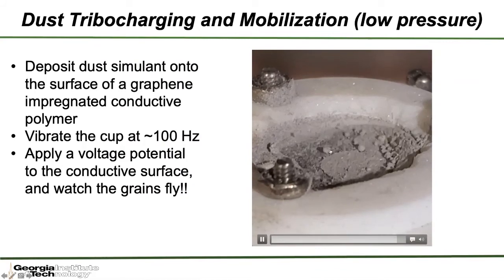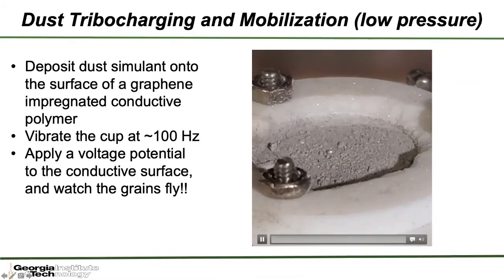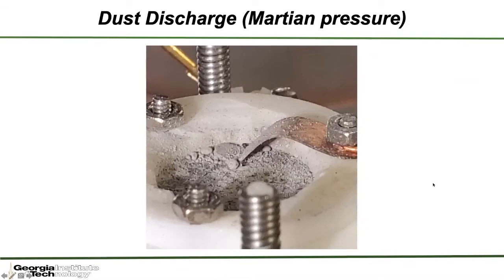Another experiment that I did is not really relevant to the Earth environment, but you could see maybe what this could look like. It's something more along the lines of a Martian pressure. I will note that this is not a Martian composition. This was very much just a test experiment, just to show you the effects that can happen when you get this electrostatic charging of dust grains.